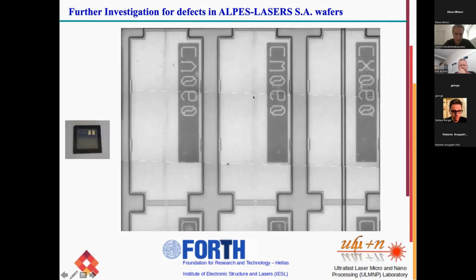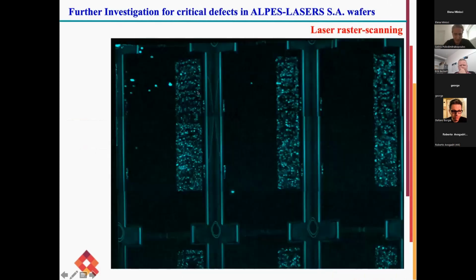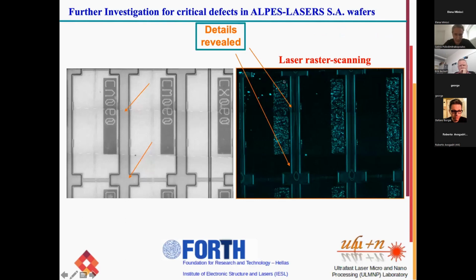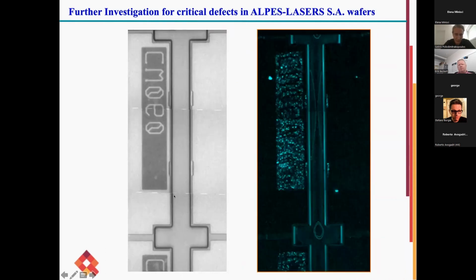And here is the CCD image from our microscope. And here is the image that you can see if we use the laser raster scanning technique that I just described. By comparing the CCD image and the image formed by our microscope, you can clearly see fine details here that cannot be seen in the surface of the sample. Those features are below the surface and we can clearly reveal them. So in case there is some defect or damage below the surface, we can identify it with our raster scanning microscope.